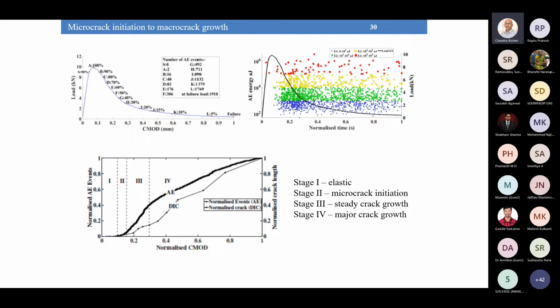So we can identify 4 distinct regions. First region, where there's no cracking, no crack propagation, we call it stage 1, the elastic stage, the linear elastic stage. The second stage is the micro crack initiation stage. So you can see a lot of micro cracking which has occurred here.